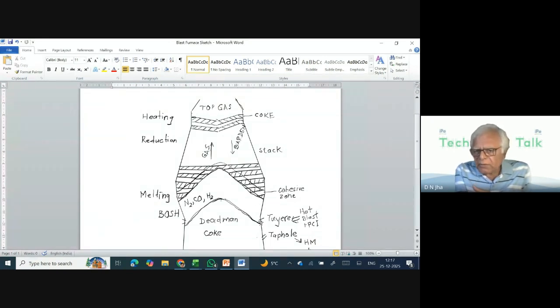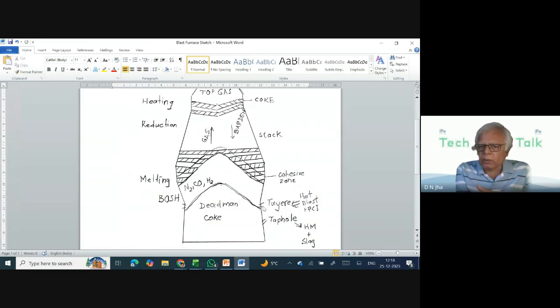So here in front of the tuyere, what do we have? We have the carbon which has fallen from the top, in the form of coke. We also have the carbon coming from the PCI, and the oxygen from the hot blast. The blast may be enriched, and therefore may not have only 21% oxygen. If it is enriched by 6%, the blast will have 27% oxygen. If it is enriched by 8%, the blast will have 29% oxygen. This is what we call hot blast. Along with that, the PCI is also present here.